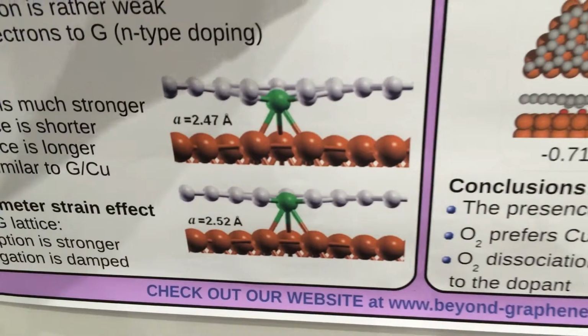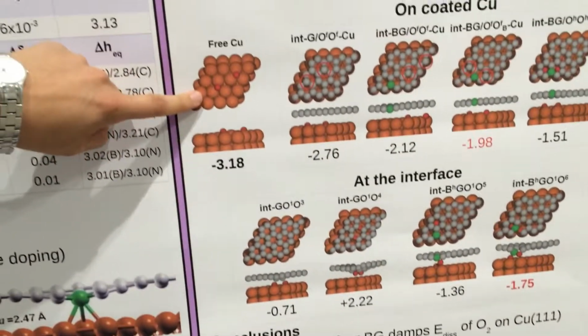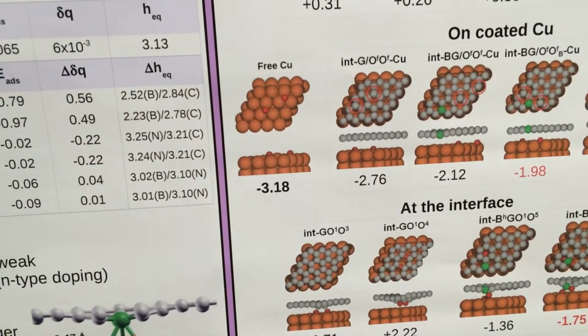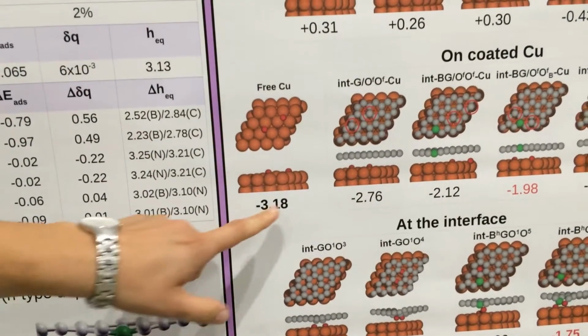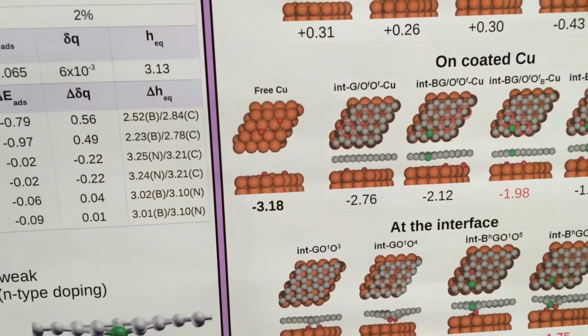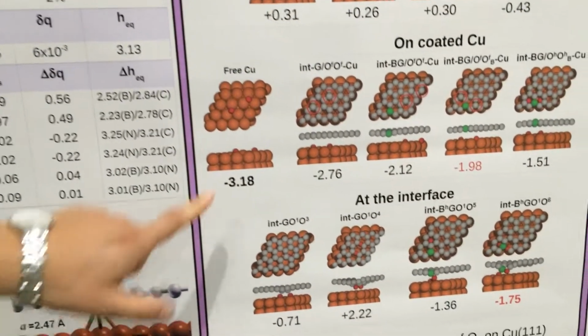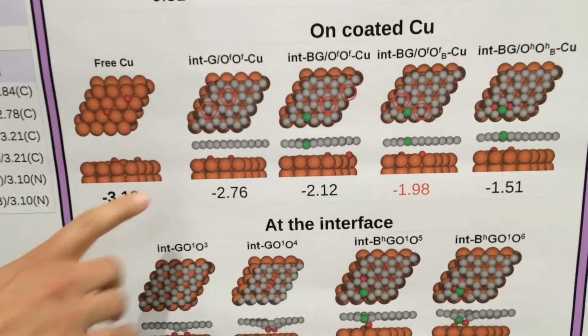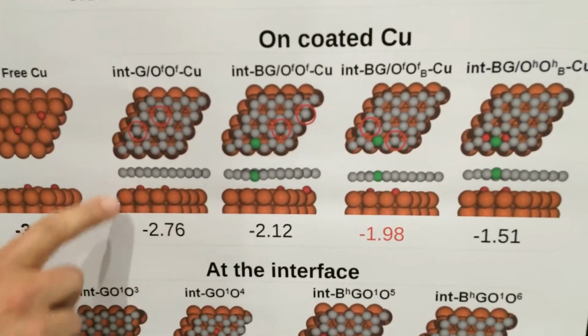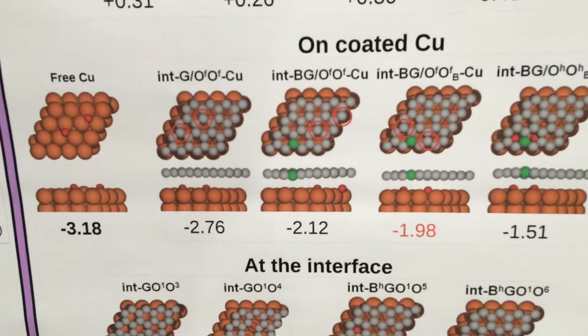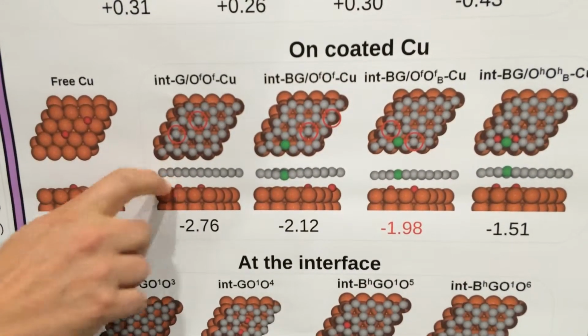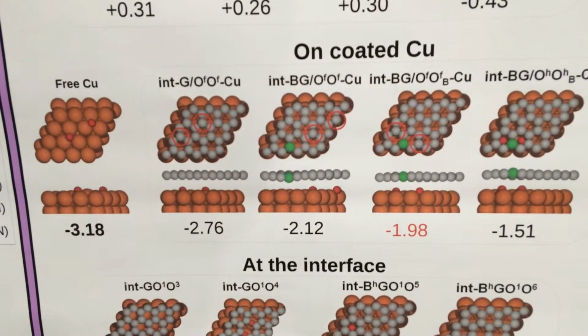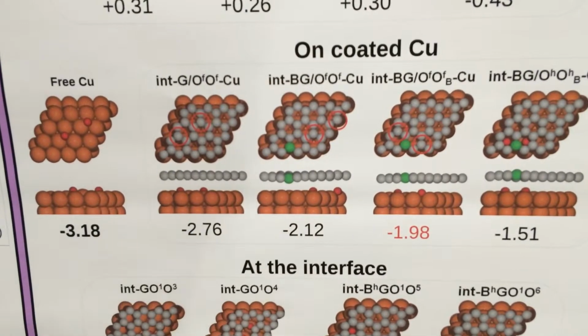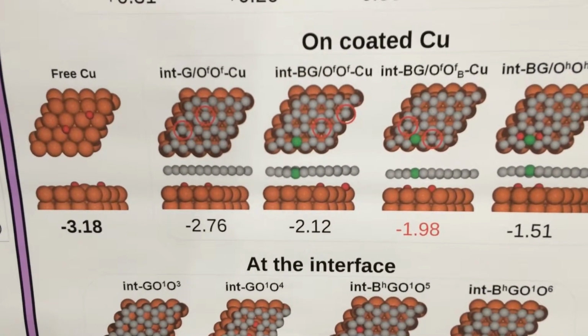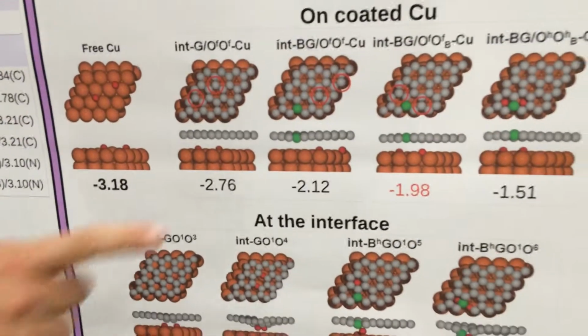Now you could think about dissociating oxygen on a pure copper, and you will see that it would be very favorable. Indeed, the copper really wants to be oxidized by air. Then think about dissociating oxygen at the interface with the graphene. If you get oxygen through, then it would really want to dissociate on the metal. But if you have boron-doped graphene, the situation is completely different.